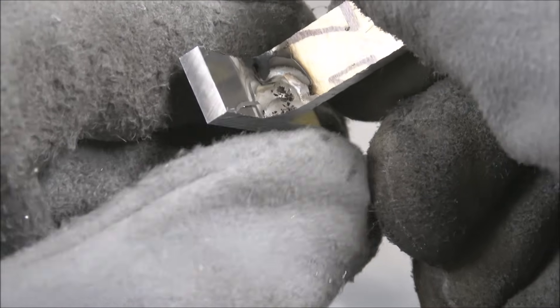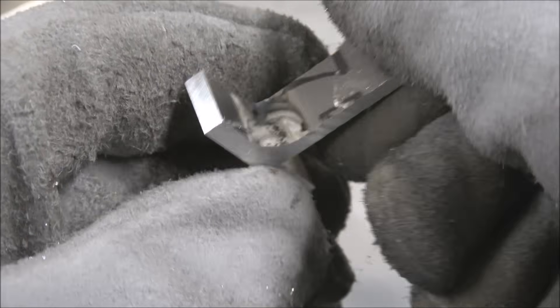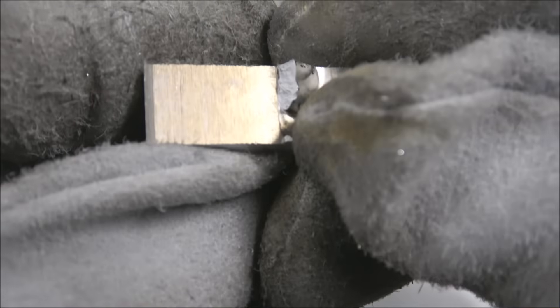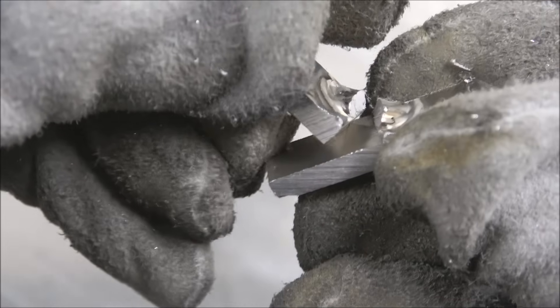5356. See how that just snapped right off. Looked like it was biting in good but it didn't make a good bond. Okay, I'll try just this little piece of that new filler rod. So that one broke off pretty easy too, but it broke off right in the middle of the filler rod. It bit in and bonded good to both of the 7075 sheets.